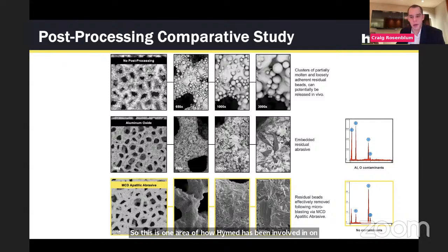And it's something that I find quite interesting in the sense that the MCD blasting conventionally was simply used to roughen the surface prior to the application of a coating, much like the titanium plasma spray coating, which I had spoken about earlier. But now we're able to find a solution for a new problem using a pre-existing material, simply applying the material and applying the process in a different manner based on the needs in this problem.